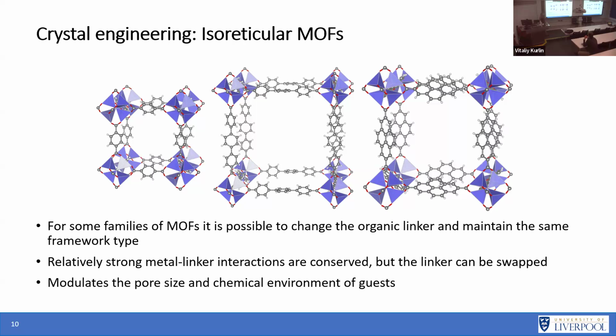But if you keep those zinc clusters the same and you extend the linker like so, you've got one with three benzenes in here, you can have the same overall structure, but a different pore geometry, so a different pore size. And similarly, you can keep it the same again, but you can actually functionalize the linker in this case. So here we've got a much more complicated linker. And this again changes the properties actually within the pore as well. So this just allows you to keep the same overall topology, but change the pore diameter and lots of different things about the pores. And it allows us to modulate the pore size and also the chemical environment of the actual guests that go into the framework.